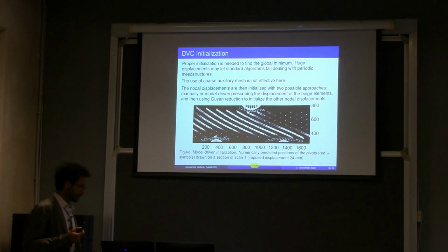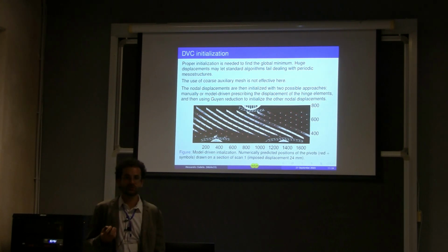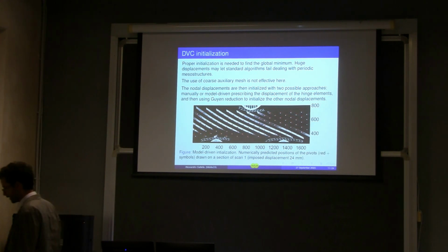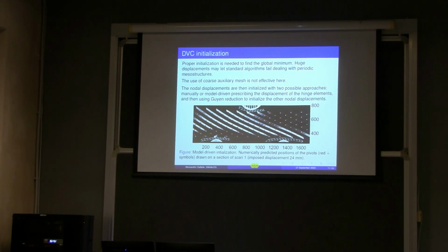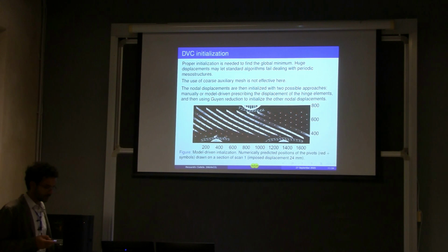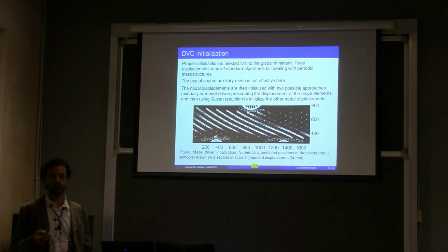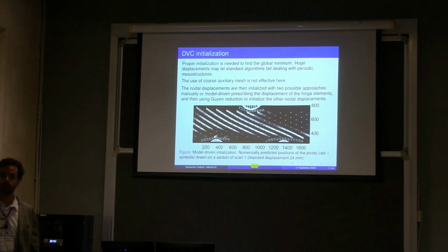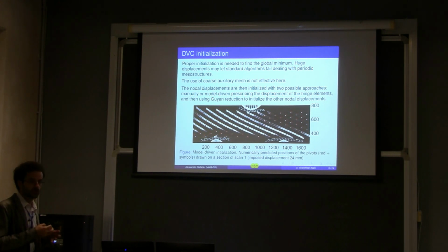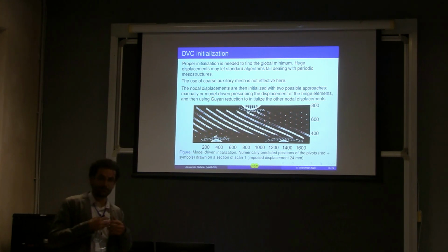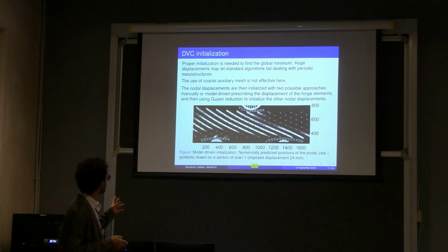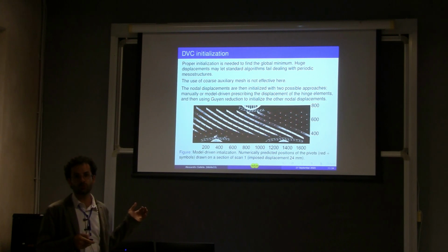Basically, we considered the continuum model proposed by Steigmann and others recently, to prepare some numerical simulations that we could use to predict the position of the pivots, and then, using static condensation, prepare a first guess for the displacement of each node of the mesh.